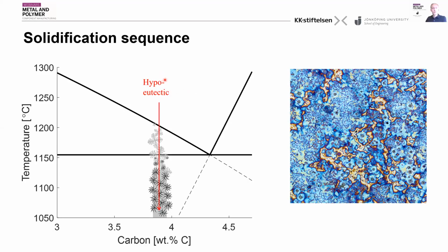So hypoeutectic cast irons, where you have a relatively low carbon content or carbon equivalent, tend to solidify in a way where this dendritic structure begins solidification. And after a while, eutectic cells or graphite start growing in the room between the dendrite arms. While when you have a near eutectic cast iron, then the eutectic cells and these branched dendritic structures tend to start to grow pretty much at the same moment, and they grow more in parallel.